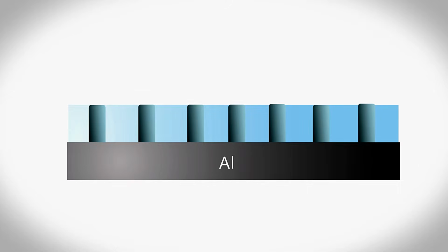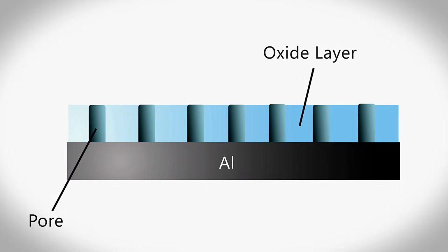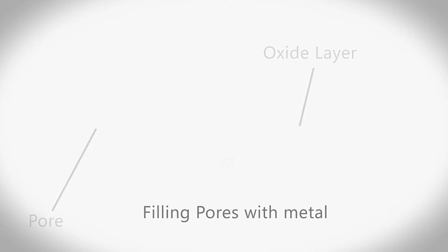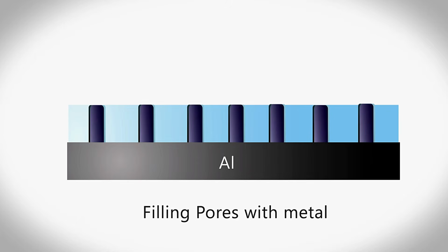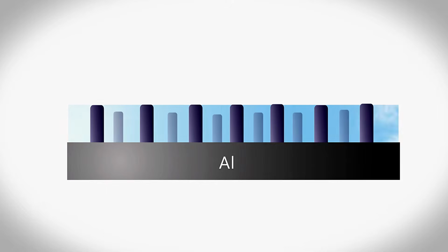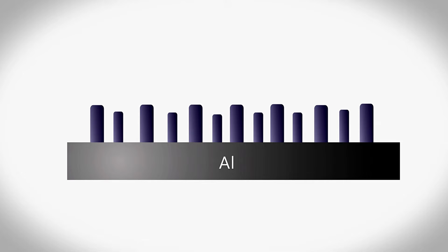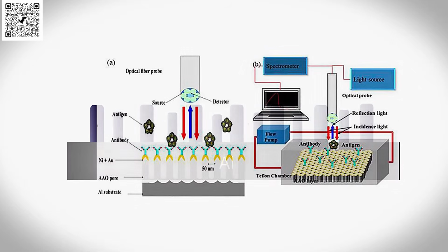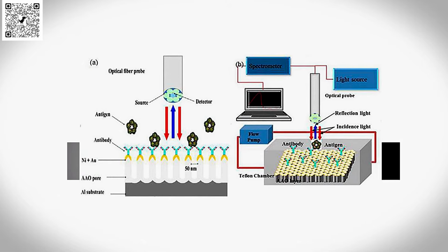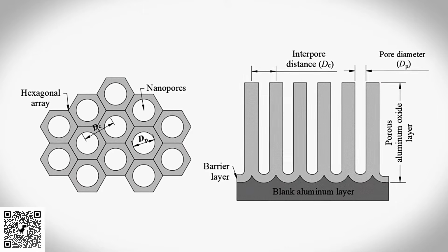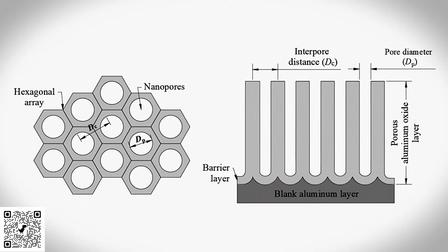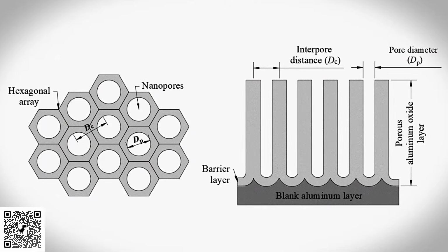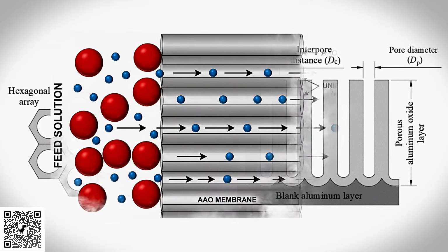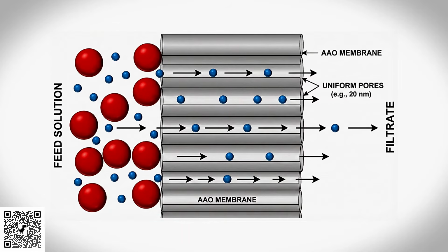Researchers now use anodic aluminum oxide as a template. Fill the pores with metal or polymer, dissolve away the alumina, and you get forests of nanowires or nanotubes for sensors, catalysts, and energy devices. AAO membranes are also being explored as ultra-precise filters for water, DNA, and even viruses. The pore size is so uniform, you can select what passes purely by diameter.